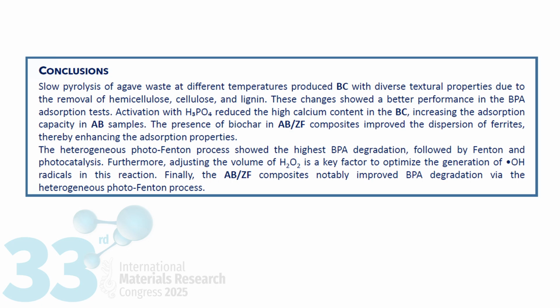Conclusions. Slow pyrolysis of agave waste at different temperatures produces biochar with diverse textural properties due to the removal of hemicellulose, cellulose, and lignin. This change showed a better performance in the BPA adsorption test. Activation with phosphoric acid reduced the high calcium content in the biochar samples, increasing the adsorption capacity in the activated biochar samples.